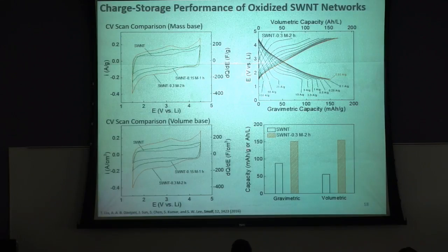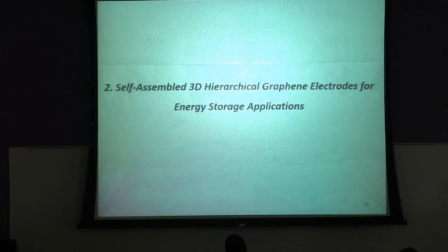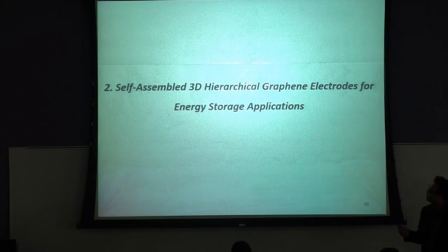So then, if we compare the single-walled carbon nanotubes and oxidized single-walled carbon nanotubes based on mass and based on volume, we can get high gravimetric and also high volumetric capacity, around 150 milliampere hours per gram or 100 ampere hours per liter. Okay, so this is related to the carbon nanotubes. So let me switch a little bit. Let me switch the topic to graphene materials now.